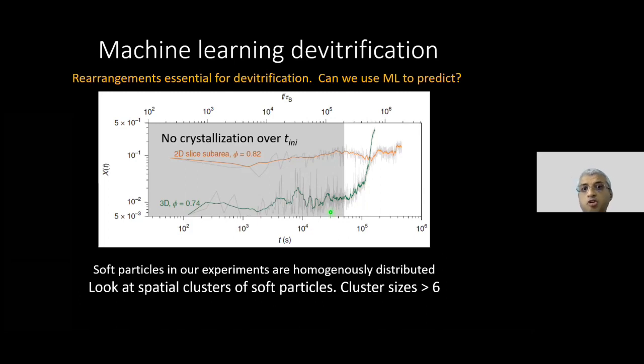Okay, and I'm going to go one step above the simulations. I am not just going to look at soft particles, I'm also going to look at soft particle clusters. I'm going to look at cluster sizes that are greater than 6, and we found that this worked great for us, and that's why we are doing this. I have no other justification for looking at a cluster size greater than 6.